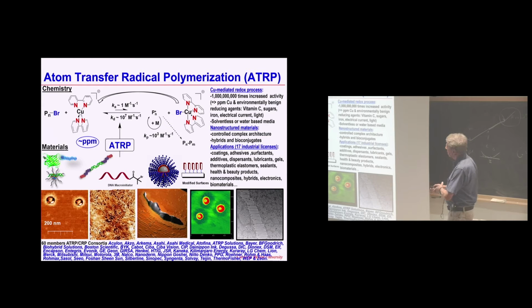So in order to run the reaction to higher conversion, I need to regenerate these activators. This is done in the presence of a very mild reducing agent. You can use something like ascorbic acid, even a little bit of sugar, maybe iron. You can also use an external field: electrical current, light, sometimes mechanical forces. You can run these reactions without solvents, sometimes in water. As I mentioned, it can be a heterogeneous or homogeneous system. And of course, the point is not to make homopolymers. The point is to make complex molecular architectures, whether something resembling these hairy colloidal structures, molecular brushes, which you will see later, and bioconjugates, growing polymers from the surfaces of even liquid metals, but also surfaces of any nanoparticles, or from flat surfaces, dramatically changing lubricity and friction coefficients.